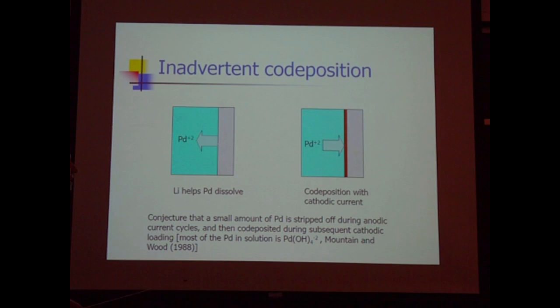But if you have a palladium reference electrode, you've got your cathode, you've got your anode wrapped around, you've got another palladium electrode sitting there. But if it's a reference electrode, it's not cathodically biased, which means it's not cathodically protected, which means it's going to be dissolving slowly. And if it's dissolving slowly, it's giving you a constant supply of palladium for your electrolyte.